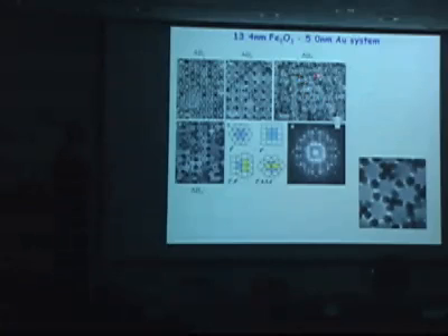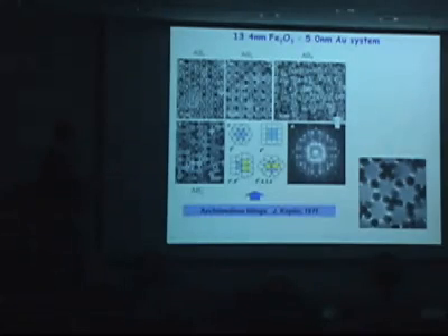In that case, we found that we form self-assembled superlattices that have both square and triangular motifs. They might look messy and pretty complex, but electron diffraction patterns show that they are perfectly long-range ordered. We have some more complex structures combining squares and triangles. It took us years to understand what type of packing motif we end up with. It turned out that this structure can be mapped onto something known as Archimedean tiling.